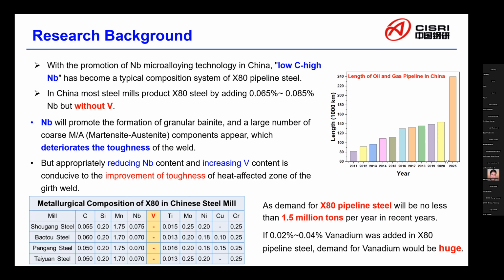However, in recent years, weld failure accidents have occurred in high-grade pipeline projects, especially in the girth weld. Niobium promotes the formation of granular bainite, and a large number of martensite-austenite components appear in the structure, which weaken the toughness of the weld. With the increase of niobium content in the base metal, the low temperature toughness of the weld decreases.